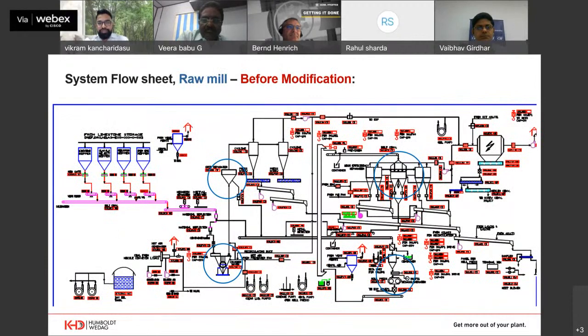And coming to the raw mill section, it is a different circuit from what we are seeing in finish mode in roller press today, because at that time in the 80s there was no V-separator. So the drying function and also size reduction were done in a pneumatic hammer mill. From this, the material is lifted to the static separator. From the static separator, the rejects go to the roller press circuit, and the recirculation material from the roller press circuit goes to the dynamic separator, and product collection takes place here and is then transported to the blending silo. Rejects go back to the roller press circuit. So this is a completely different circuit from what we see today.